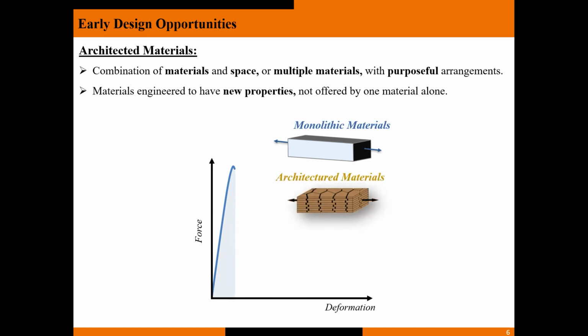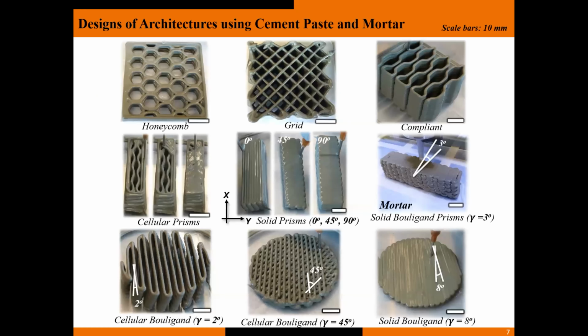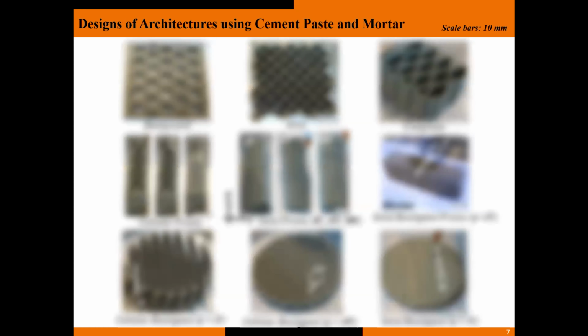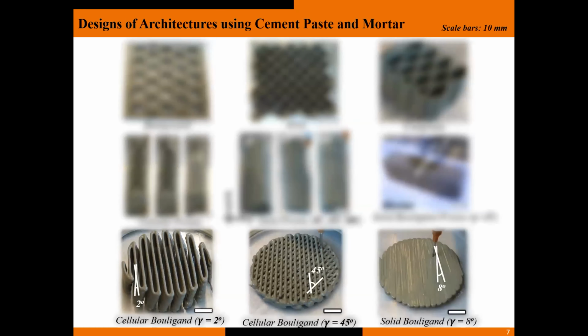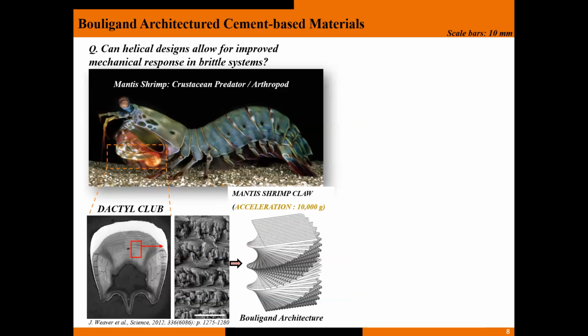You apply the force in a brittle system, the material fails. In an architected material, you have the ability to tune the response by tuning the architecture and then perhaps improve some of the properties. So we looked into a number of different architectures, as you can see here, but more specifically, I'm going to very briefly talk about these Bouligand and helical architectures in which, as you deposit the materials in a layer by layer fashion, you continue to rotate the orientation.